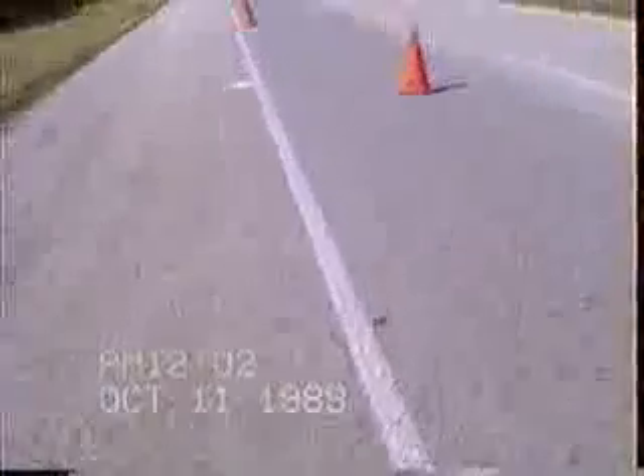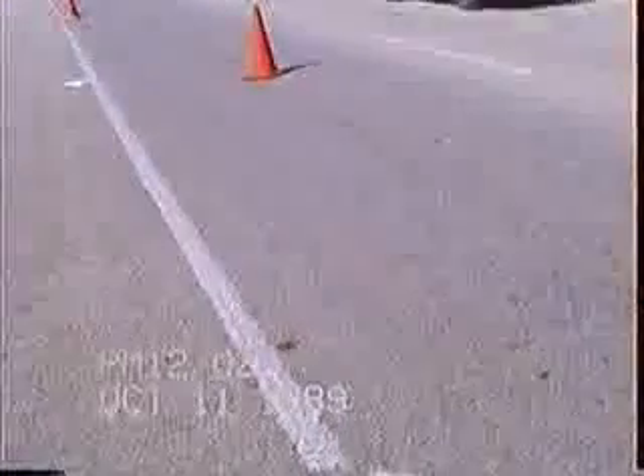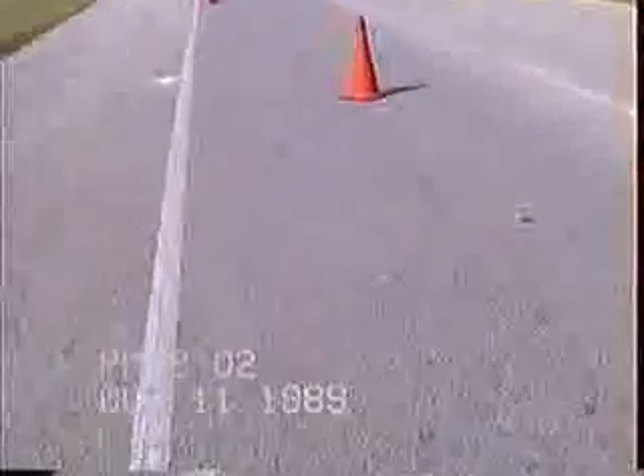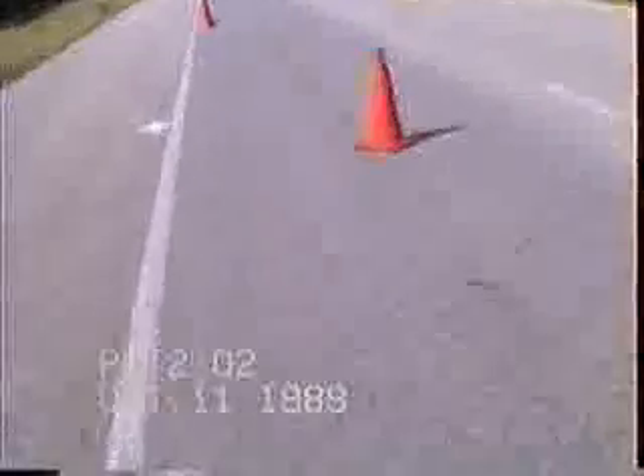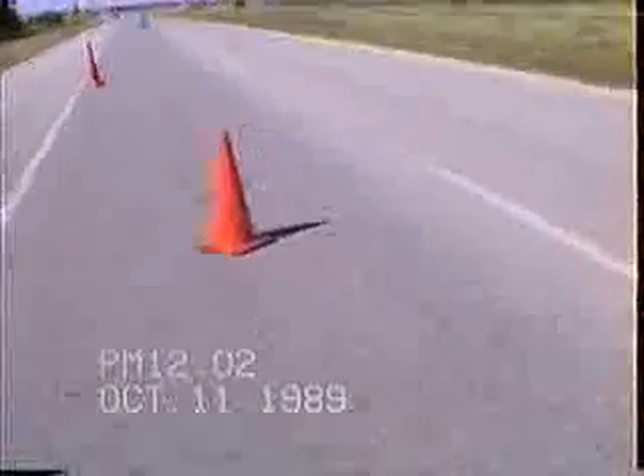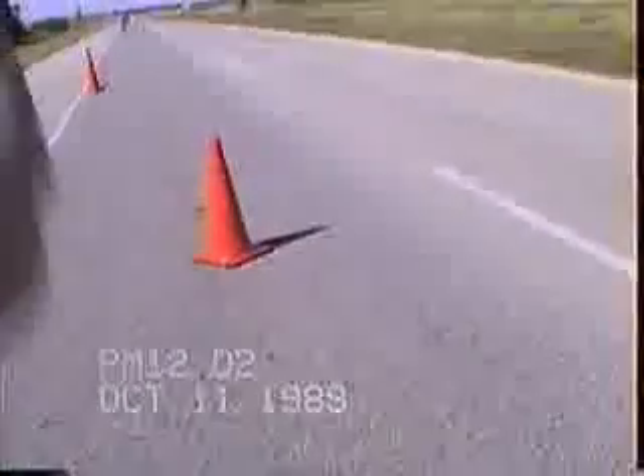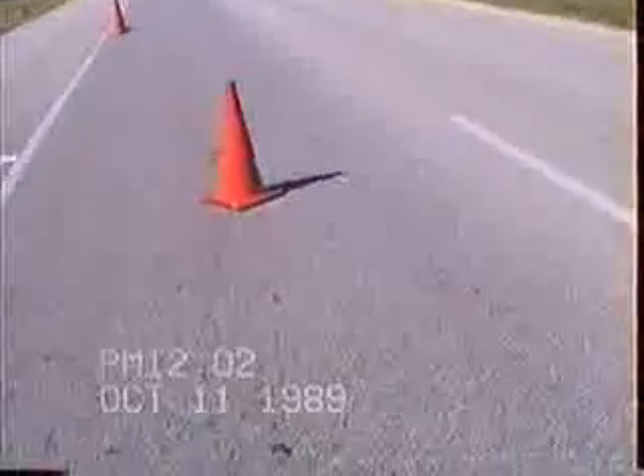What happens is what we have here is about 2 inches of a HMAC surfacing or wearing course and 8-inch sand asphalt base. And as water penetrates into the crack, problems with sand asphalt eroding and with the fine-grained soil underneath eroding as well. Where we have our greatest rutting and where we have some associated fatigue cracking is where I believe a thermal crack is open in the longitudinal direction in the inside wheel path, which is about in the center of the pavement.